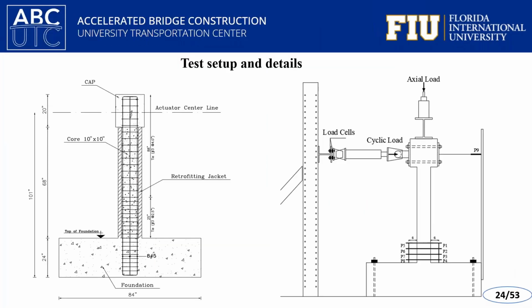This figure shows the test setup for experimental program, which is same as previous project. Each column was first subjected to a constant axial load. The cyclic lateral displacement were applied using actuator. Linear potentiometers were used to measure lateral displacement and curvatures along the plastic hinge region. Strain gauges were also attached to reinforcement rebars to capture local behavior.